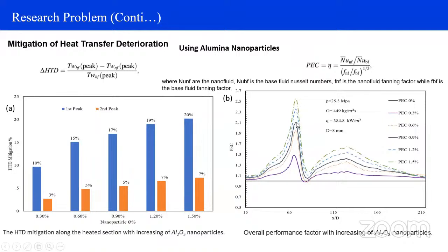Same like if we check overall performance, this one, I use here 1.5%. When the concentration of nanoparticle is 1.5%, then the overall performance is high. So it is clear from figure B that against growing strength of nanoparticle concentration, the overall performance increases against higher values of nanoparticle concentration. So it is clear from figures A and B, nanoparticles are very helpful in mitigation of heat transfer deterioration.